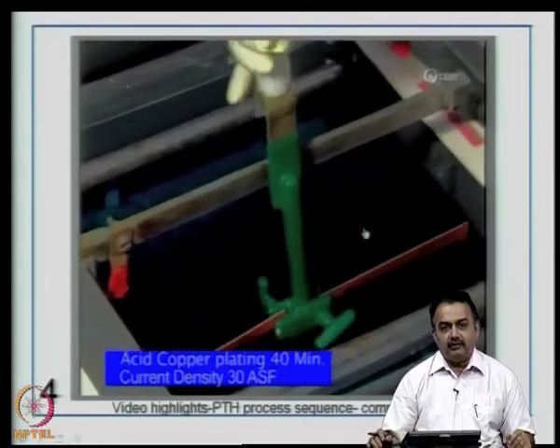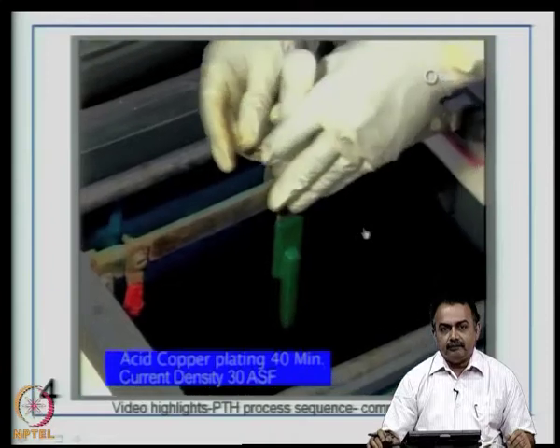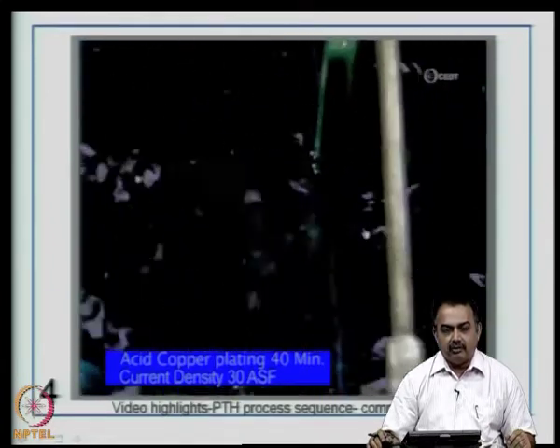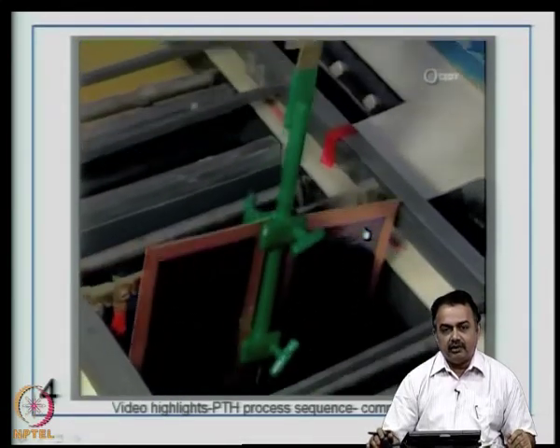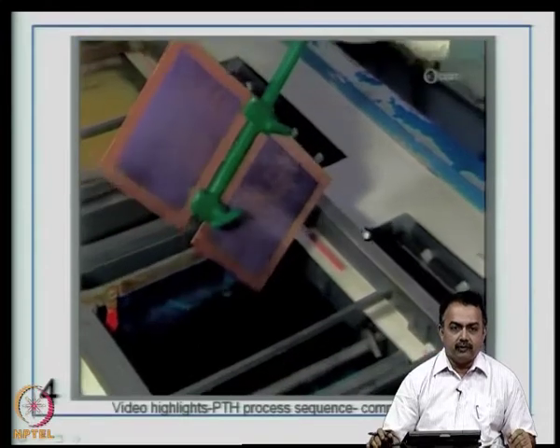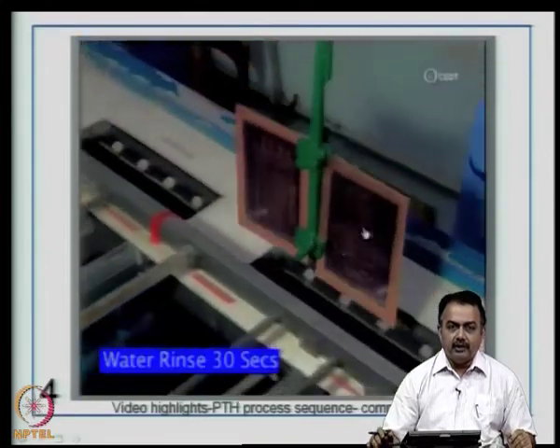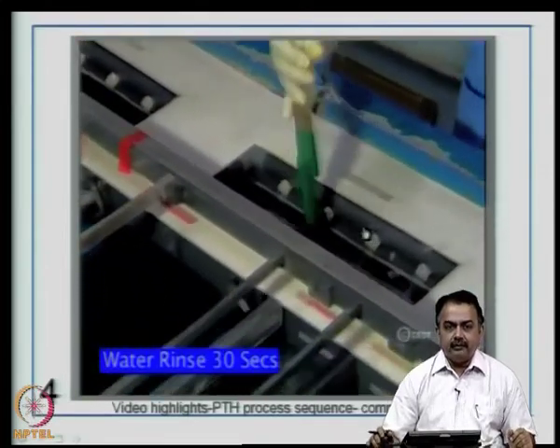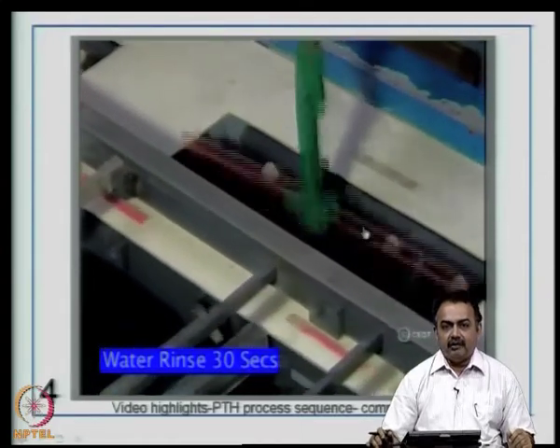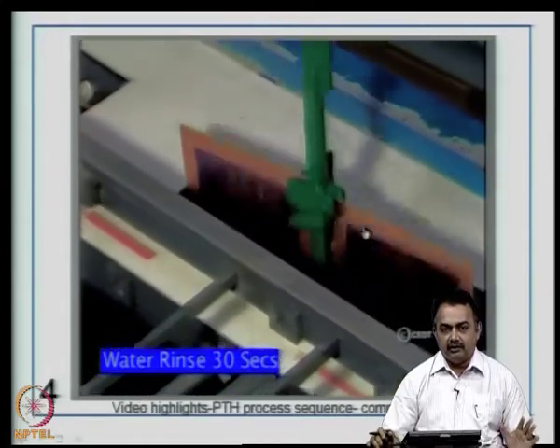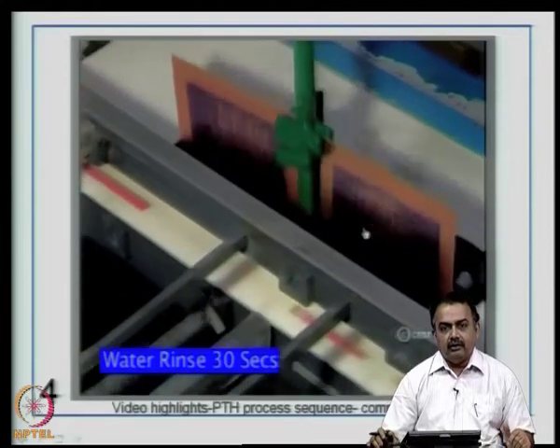Another aspect that you have to see here, as we watch this video, is the electrolyte, the acid copper bath. Typical timings are indicated here, about 30 to 40 minutes at 30 amps per square feet, and you will get about 20 microns deposited. Again, you see here, after every process there is a water rinse to avoid contamination.